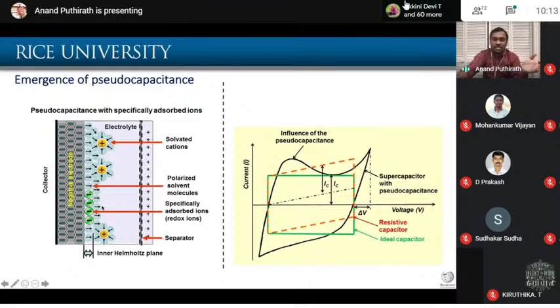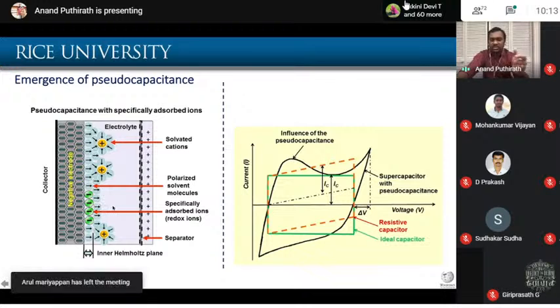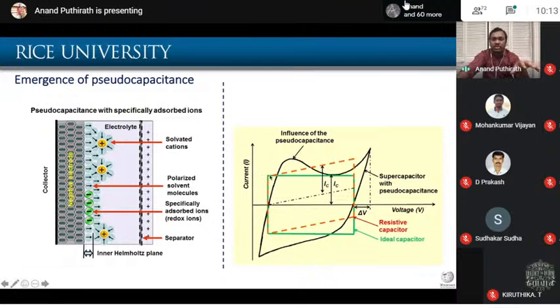Here it's not full oxidation, it's a partial oxidation I will be discussing shortly. But if it is a normal, nice capacitor, only EDLC, electrical double layer formation, you will see a nice flat curve. And if your system has parasitic resistance, your electrode has some high resistance or the electrolyte has high resistance, then you will see a slanted curve for a supercapacitor. We used to say, okay, it's a supercapacitor, but with high resistance.